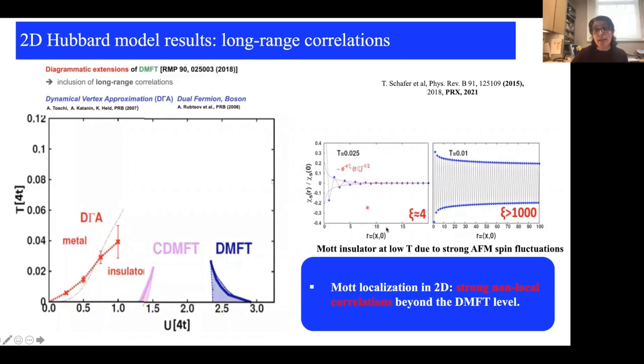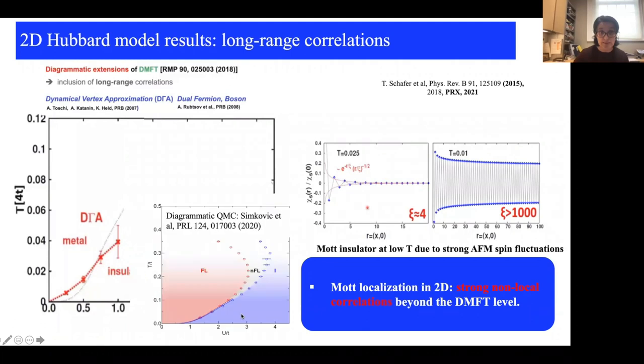It was shown that the origin or the nature of such strong suppression is due to strong antiferromagnetic spin fluctuations, which are more dominant at lower temperature and are long range. So this is the correlation length shown here, how it changes with temperature, indicating that in our DCA calculation, we really have to go to larger clusters to capture this small U behavior for the metal insulator transition.